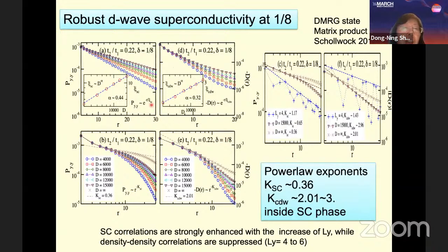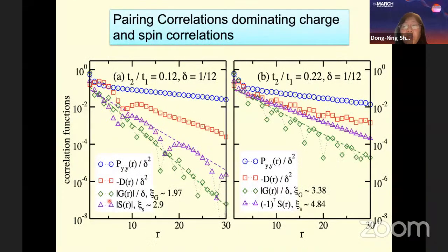Here is another example. The previous results used a doping level of 1 over 12. Now we look at the doping level 1 over 8 with a larger T2 over T1. In this case, we still find power law decay superconducting correlation with the exponent around 0.36. So for different doping levels, we always find that the intermediate phase has very robust quasi long-range order for superconducting correlations.